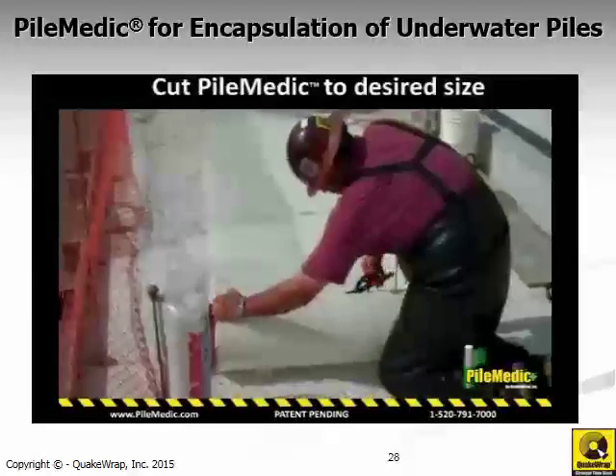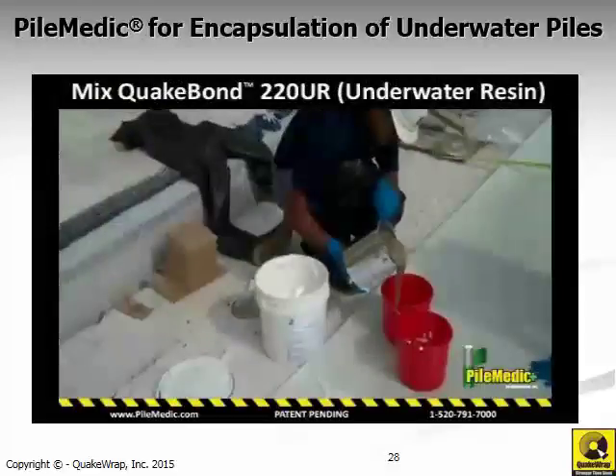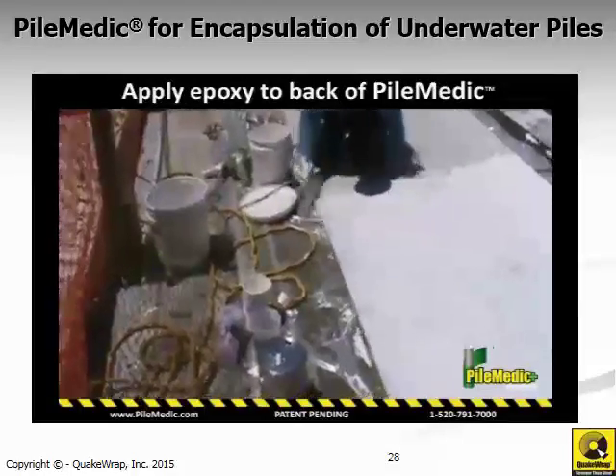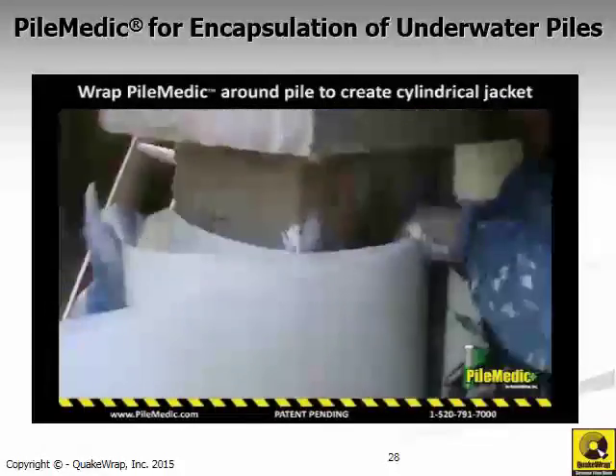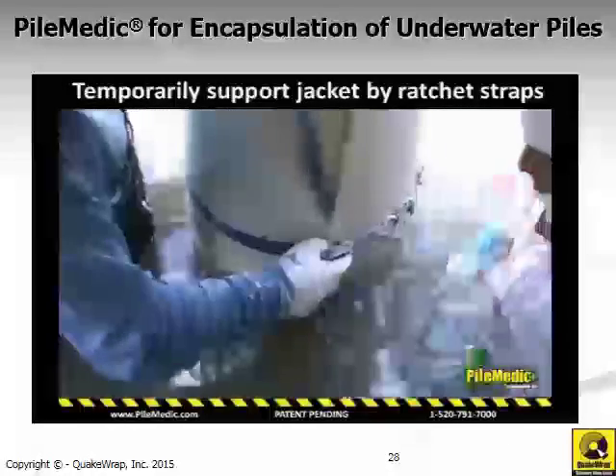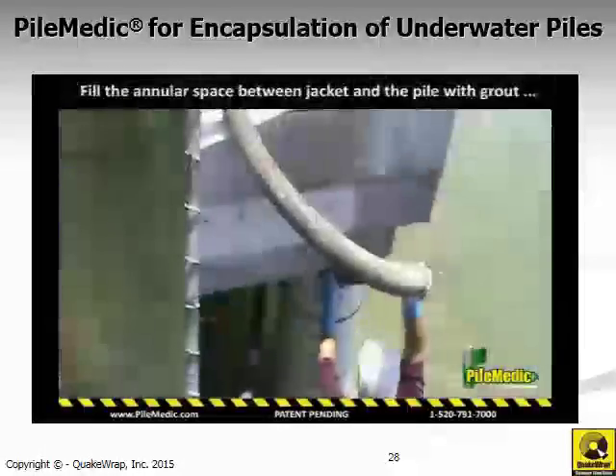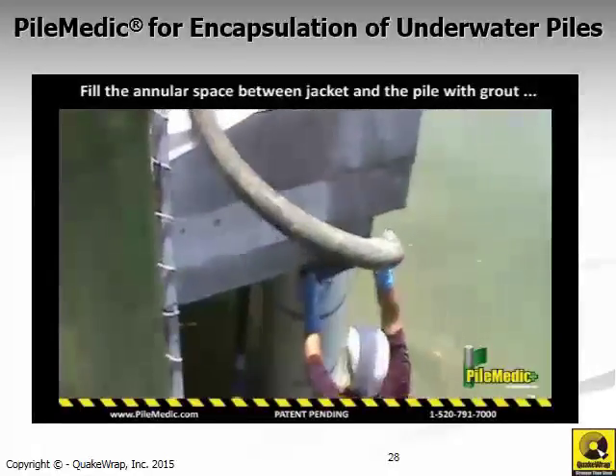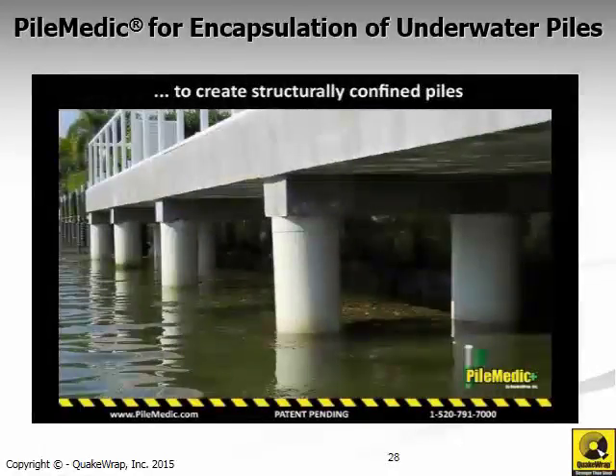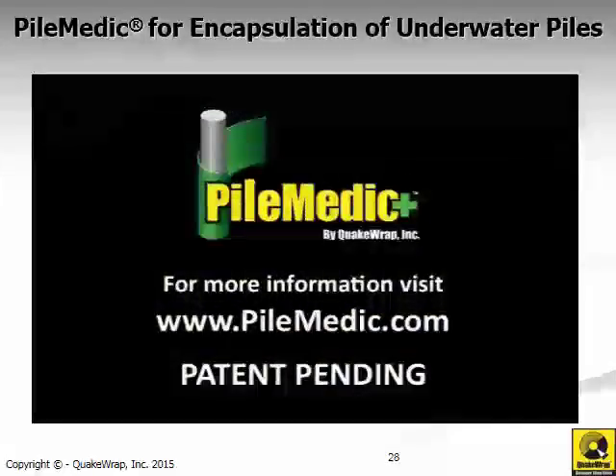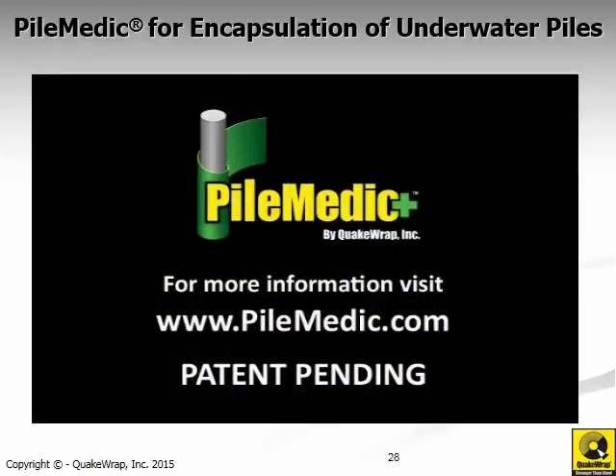Here is a video showing how we would repair that column. The worker can cut a length of this laminate to whatever length they want. This particular epoxy that we are mixing and applying cures underwater, so we do not need any cofferdams. Because the water is shallow, the workers can walk in the water and wrap this laminate a couple of times around the column, adjusting the size and holding it together with ratchet straps, and then filling the annular space with grout. This becomes the finished product of this type of application.